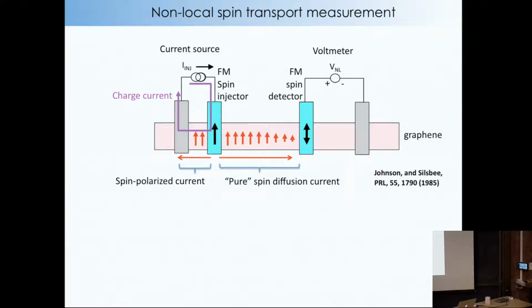And so what you do is, uh-oh, it skipped a slide. Well, what you do is you flow a current through this ferromagnet into the graphene and out the non-magnetic side. And what that does is that's going to inject a spin-polarized electron. Because these ferromagnets, they don't have equal numbers of spin-up and spin-down electrons. They have more of one than the other. So a ferromagnet is a spin-polarized material. Okay? And so when you drive the current, you're going to make a spin imbalance.